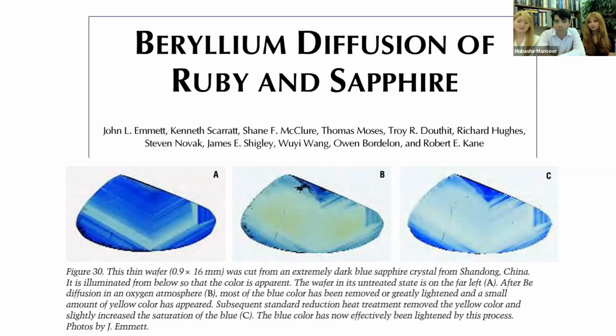However, it's enough to note that if you have a sapphire that is very dark, and if you expose it to beryllium diffusion, you can actually get very nice light colored sapphires out of it. So beryllium tends to destroy the blue color in sapphires. And beryllium is not the only element that can do this. A lot of things can, and beryllium is just one of them. So that's also an interesting topic that we'll talk about later on.